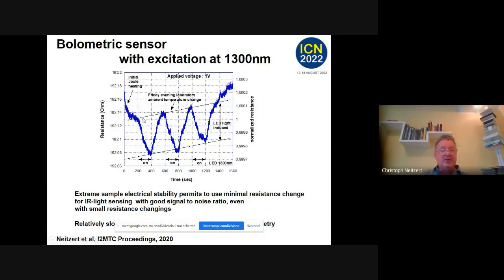So what happens now when we illuminate? We use a 1300 nanometer, low intensity, below 5 milliwatt, LED diode, no laser, no high intensity light. You see, we switch on the current. We have some changes of the resistance. This is the normalized resistance, due to Joule heating in the beginning. It's just 1 volt, we have still some heating. Then we switch on the light, we switch off the light, we switch on the light. We switch on 3 times, and we see nice modulation of the signal due to this 1300 nanometer wavelength. This is already out of scope of silicon, because silicon goes up to 1100 nanometer. Okay, so we have a bolometer, and then we have a drift.